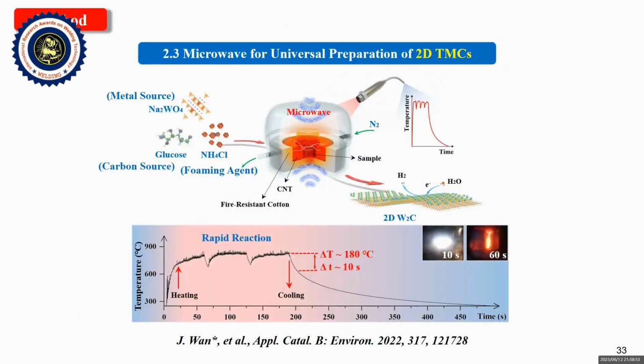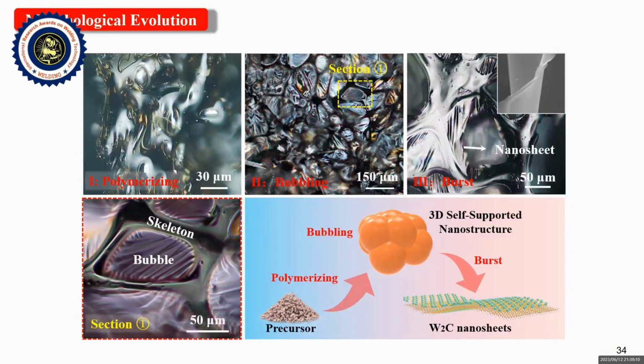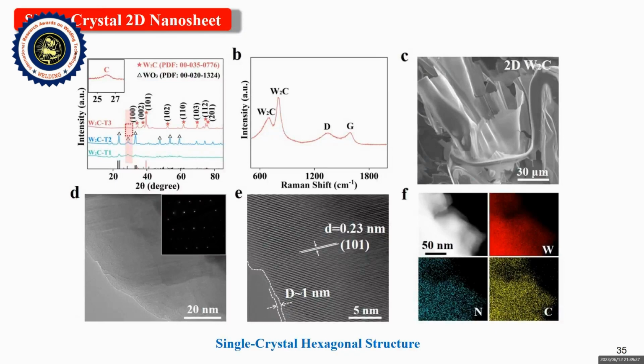By choosing the suitable carbon source, metal source, and foaming agent, we finally successfully prepared a two-dimensional tungsten carbide with microwave pulse. Because of the in situ analysis of microwave, 3 processes of polymerizing, bubbling, and burst can be clearly observed. The two-dimensional tungsten carbide exhibits a single crystal structure.